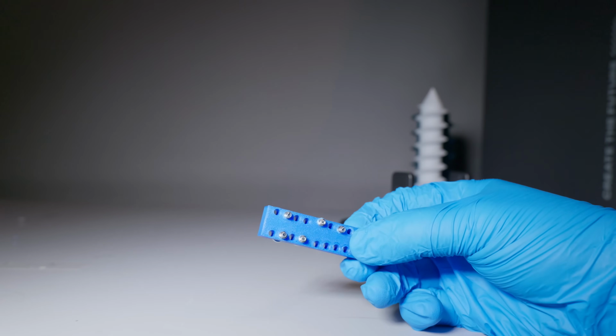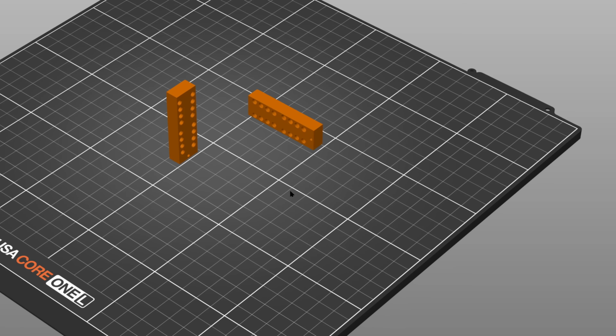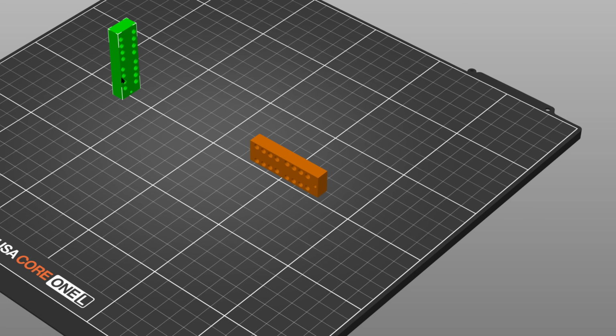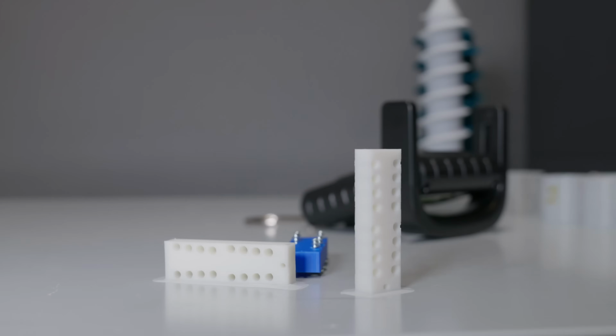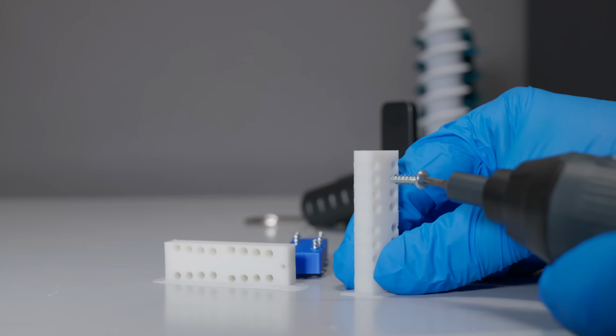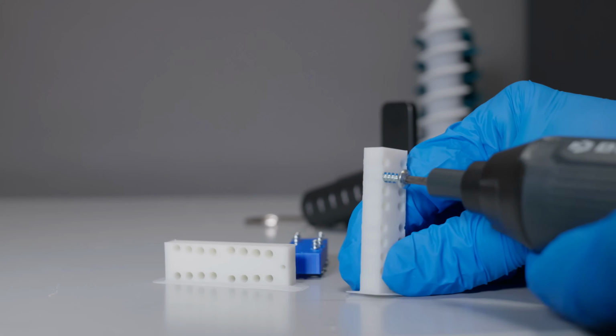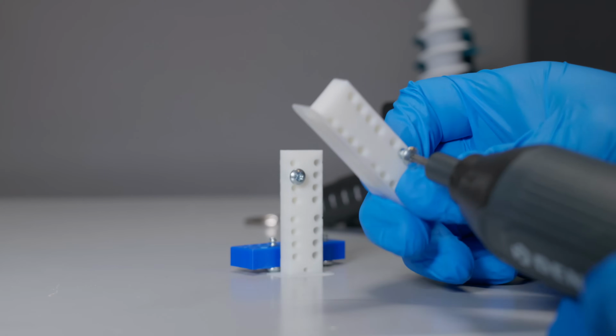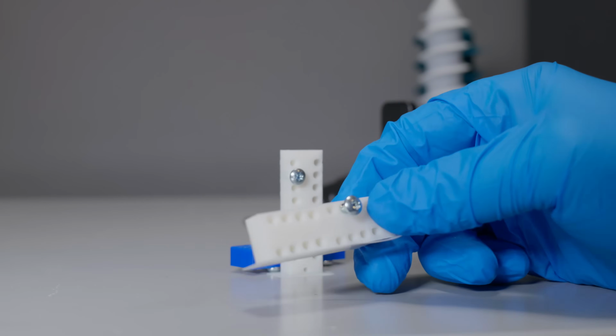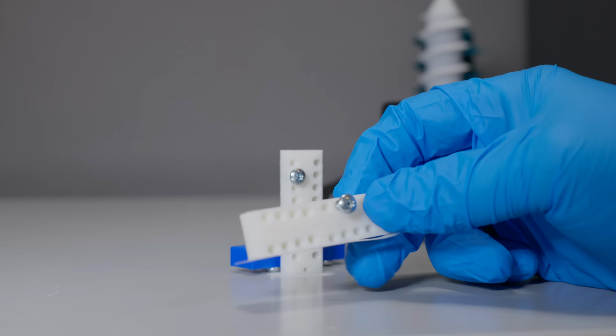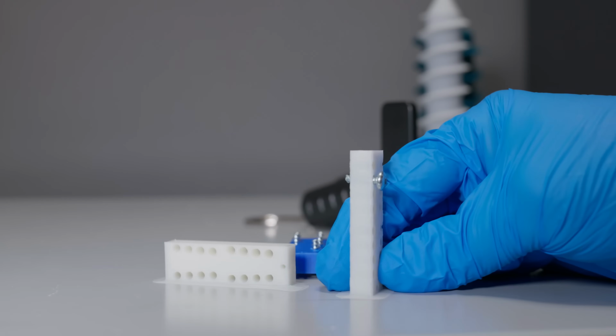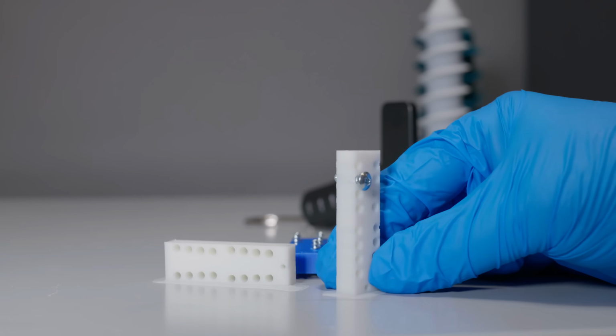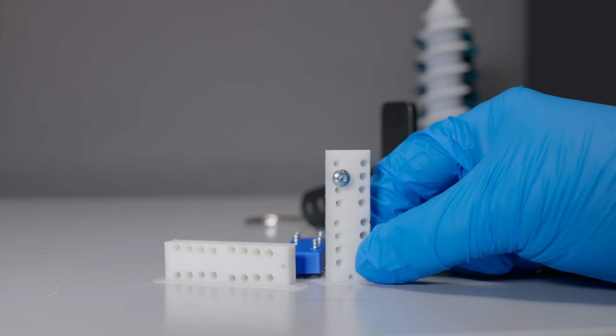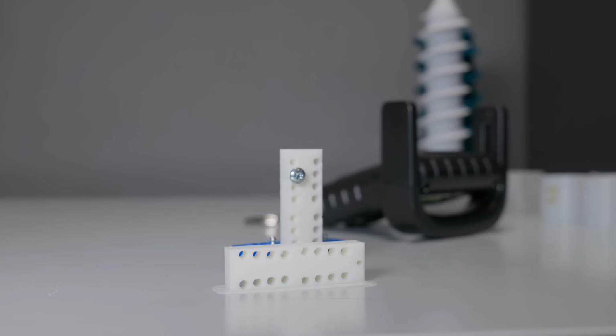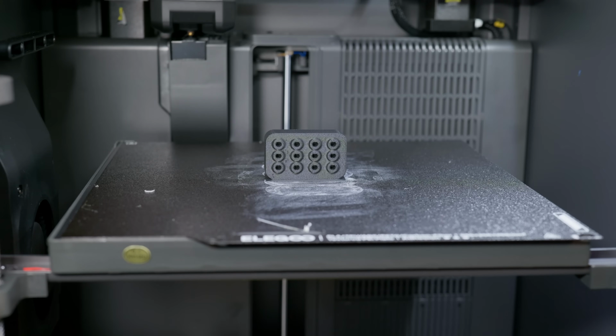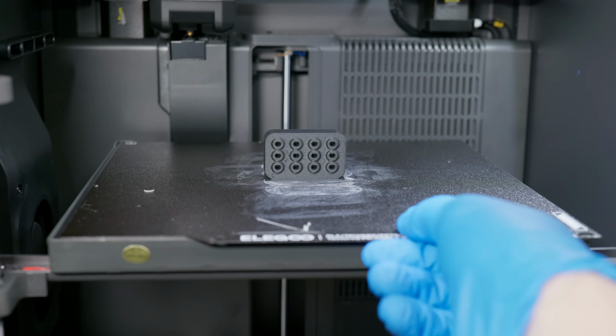What I really didn't expect, though, was that this performance would be almost nearly indifferent in most cases, regardless of orientation. Testing using normal PLA, none of the orientations of the print failed within reasonable limits, and the same for the other materials that I tested. So there's a reasonable assumption that unless you're printing with known weak filament that has terrible layer bonding, for example silk PLA, which I didn't test because it's so terrible, why would you ever try and use it for a functional part? Don't do that. But otherwise, you don't necessarily need to be too concerned with orientation when you're printing screw holes.